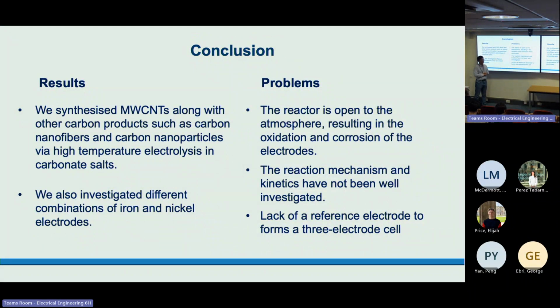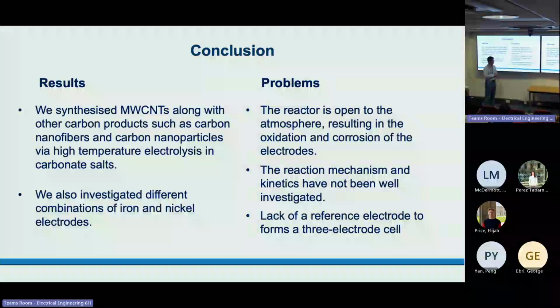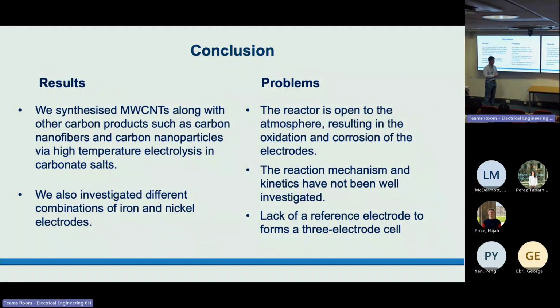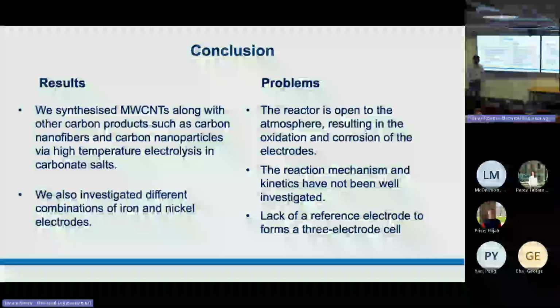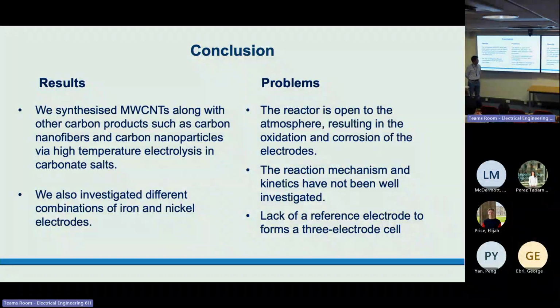But we have some problems with our current research. One is the reactor is open to the air, resulting in the oxidation and the corrosion of the electrodes before we carry out any electrolysis. And also the reaction mechanism and kinetics have not been very well investigated. And for now, we're using a 2 electrode setup instead of a 3 electrode setup, so we don't have a reference electrode to form a 3 electrode electrochemical cell.